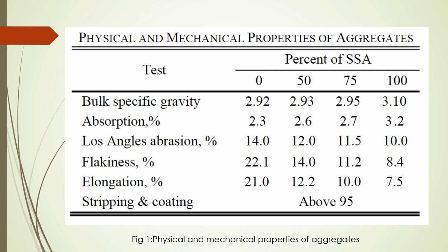Next test is absorption percentage. Its value is 2.3 when the percentage of steel slag aggregate is 0, and it increases up to 3.2 when the percentage of steel slag aggregate is 100. Next test is Los Angeles abrasion percentage. Its value is 14 when the percentage of steel slag aggregate is 0, and decreases up to 10 when the percentage of steel slag aggregate is 100. That represents the good hardening properties of steel slag as a road construction material.